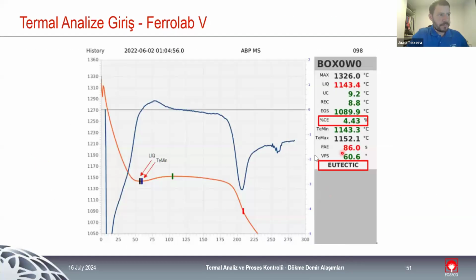So the VPS, as we discussed, is the angle that is formed at the end of the solidification. So it is the angle of the first derivative, and the first derivative is related with the EOS value, with this temperature. So normally with VPS, when it is wide open, it means that a lot of graphite transformation happened at later stages of solidification. So when we decrease the temperature and achieve the eutectic point, we have a transformation of carbon into graphite, and the temperature continues to drop. And at the end of solidification, we still have a lot of carbon in the melt to transform into graphite. And this is not good.